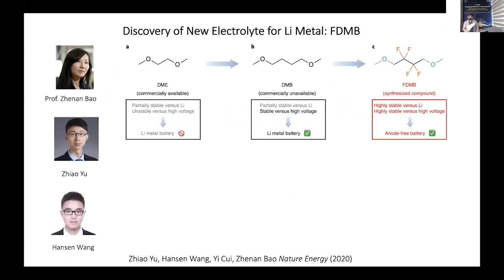So with these host material designs, of course, the interface is very important. Over the years, we developed a number of interfacial materials to try to stabilize the metallic lithium anode. And one idea to generate a very stable interface would be through the electrolyte, picking the right electrolyte reacting with this lithium metal, so that the decomposition compound can stabilize this SEI. So working together with Zhenan Bao in chemical engineering at Stanford, and our joint students Hansen Wang and Zhao Yu, we looked into this new solvent, very exciting. That's highlighted as FDMB to the right.